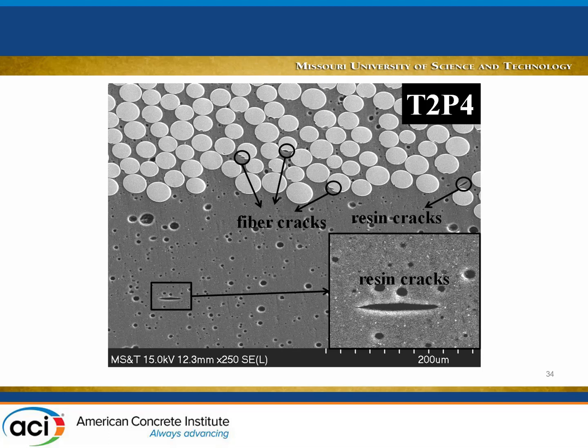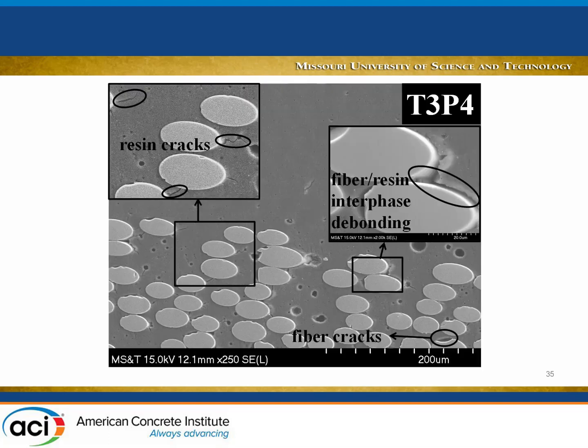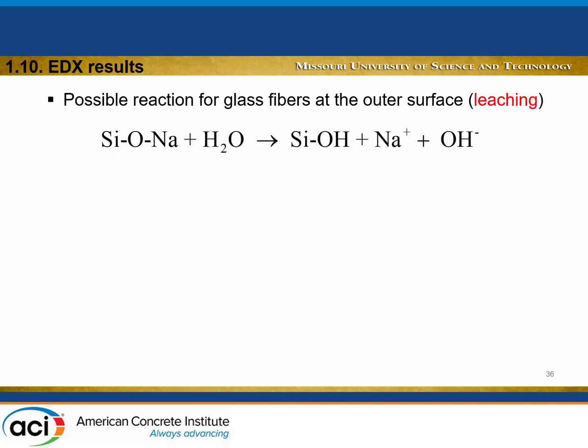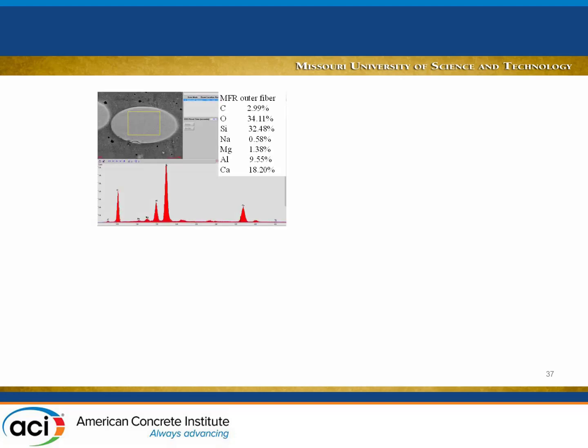You start to see also some damage to the epoxy glass fiber interface. So you see here the delamination, and some cracking as well. This is tank 3 at about 1 year, showing some damage at the microstructure level. I'm not going to go through this as we don't have too much time remaining.